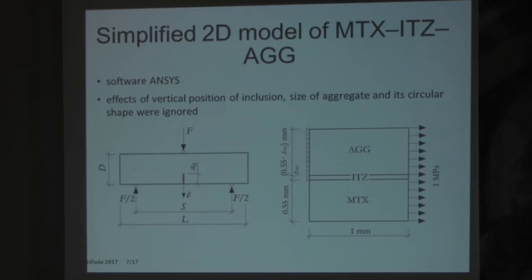It was made as a simplified 2D model which goes from the three-point bending geometry. In this geometry our specimen was tested, and the crack tip is on the interface between matrix and ITZ. It means when we loaded the specimen, the crack grows from the initial notch, goes to the matrix, and we model the interface between matrix and ITZ.